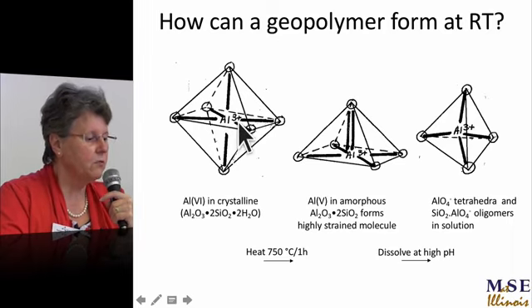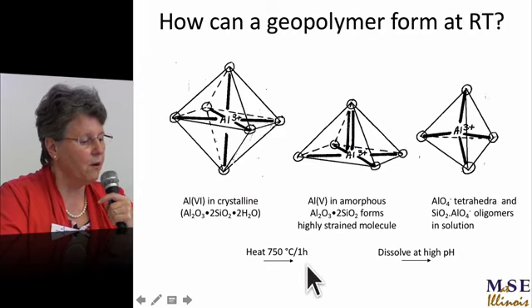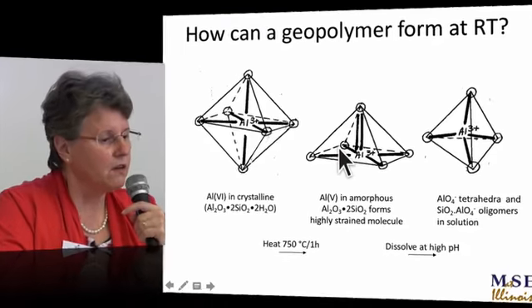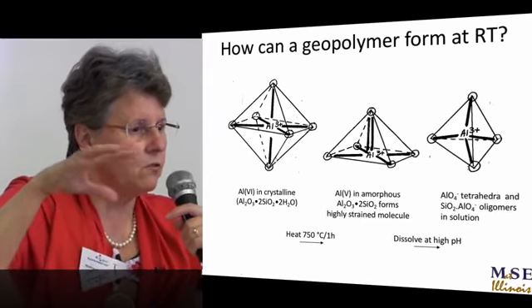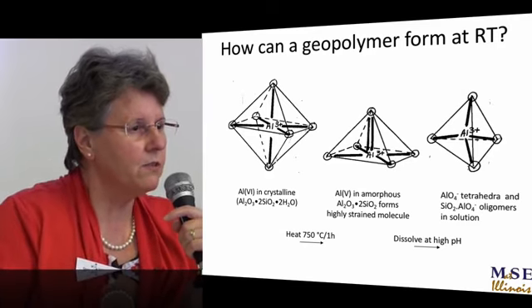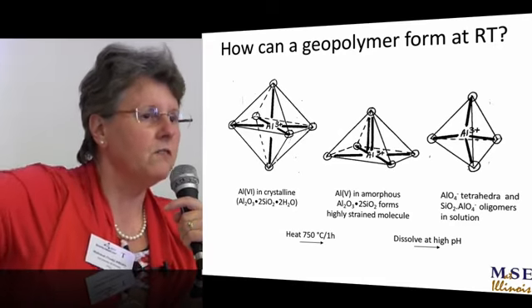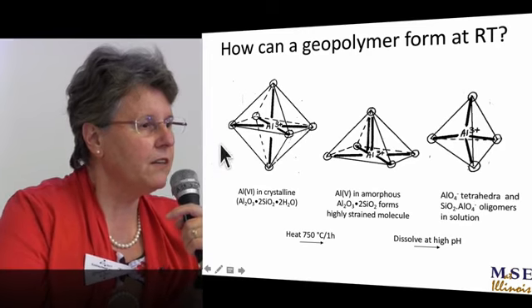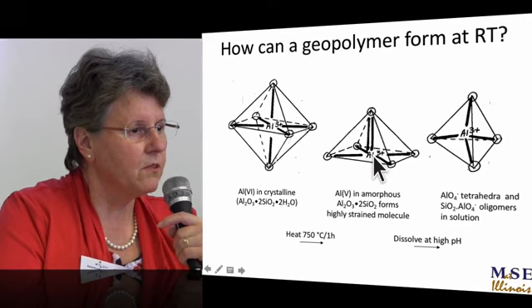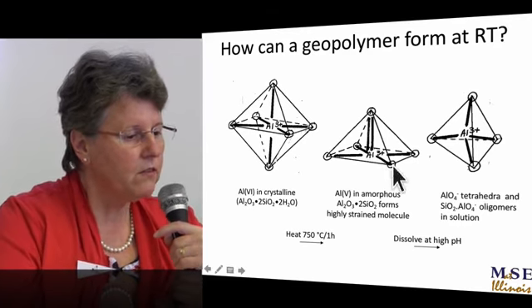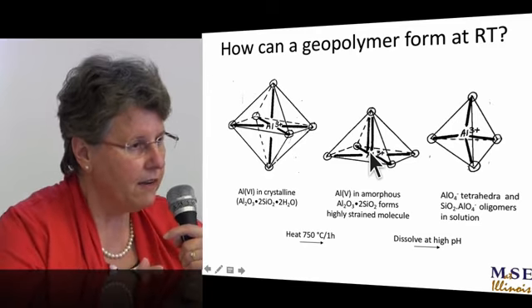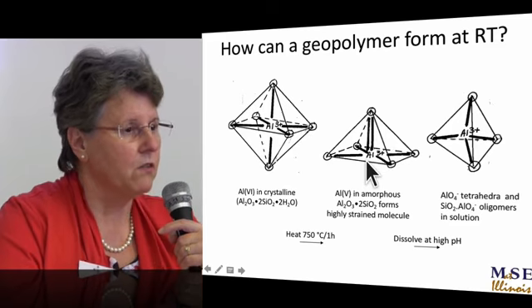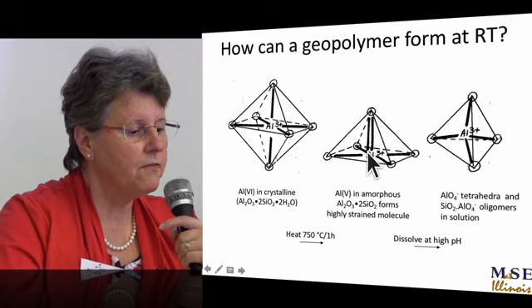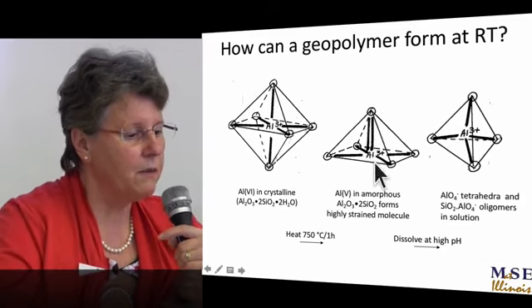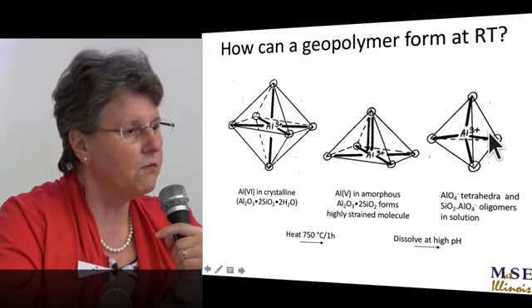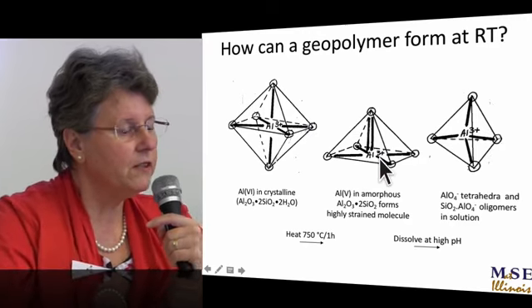Kaolinite is crystalline and the aluminum's in six-fold coordination. When you make it amorphous by heating, it goes into five-fold coordination. And this is a highly strained molecule. How come you can make a ceramic material, which usually you have to fire to 1,000, 1,200, 1,300 degrees for a long time, with long energy, and here just water can make a ceramic material? It's because when it's amorphous, the concentrated NaOH or KOH can attack this molecule, and it's so strained in this five-fold coordination that it is attackable, and it can be broken up into the tetrahedra, AlO4-, and away she goes. So that's the critical step.